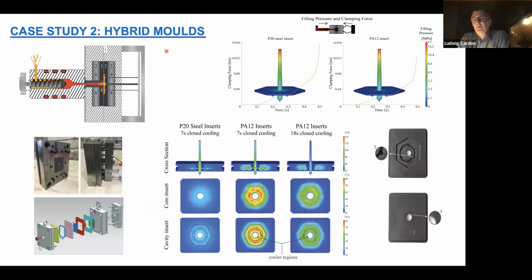But I agree that wearing of the molds, we investigated, it happens, but not too fast. So you can do 10, 20 parts in standard non-filled materials. Going with filled materials, yeah, it will be perhaps less. But we even did, with this mold you see here on the screen, something like 300 injection moldings with not so much wearing. But one important thing, pay attention: you need simulation in advance to find out the lowest possible injection and holding pressure. That's very important.